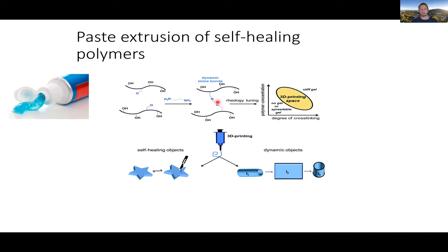And this is a really nice thing because then you can go from cross-link to decross-link with the chemistry. And obviously you want to do rheology tuning. That is based on the concentration of the polymer in your solution and also the degree of cross-linking, so how much of this you add. The more you add of this, the stiffer the gel will be and the harder it will be to flow. So you need to have a certain space where you can do this.